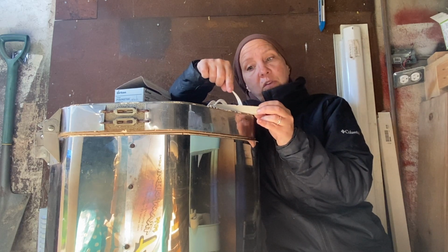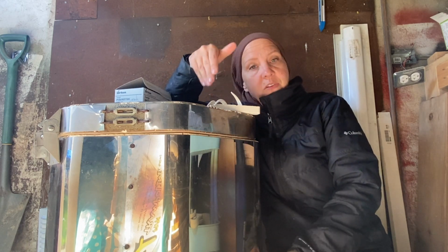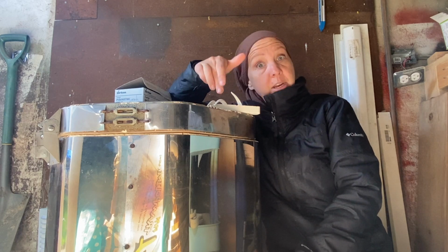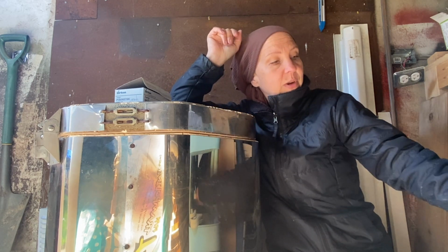And you can see this cone started to bend a bit. So this is when I would say I got a hot 6. In this case, this is my glaze firing. So I got a hot cone 6. 6 was my target. I know I met it. 7 bent a bit, so I can say I got a hot 6. So that's kind of what you're looking at for cones.